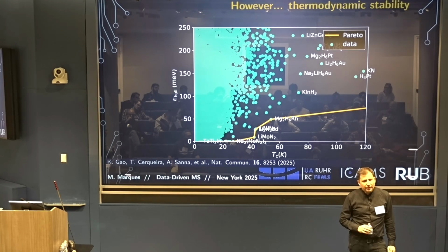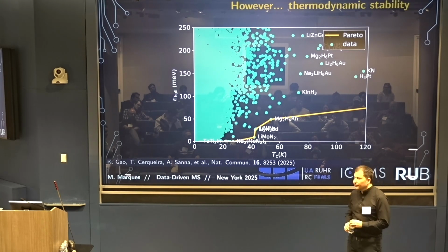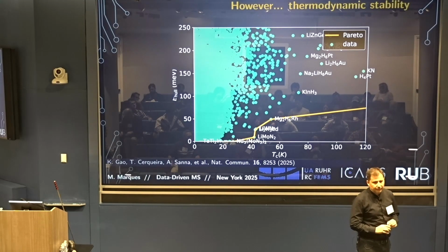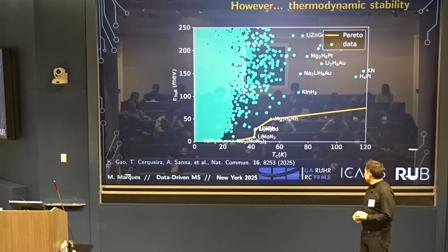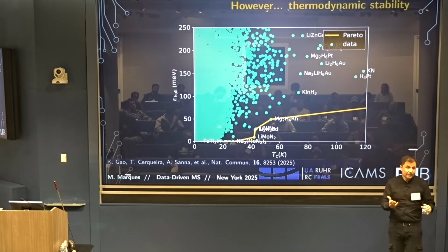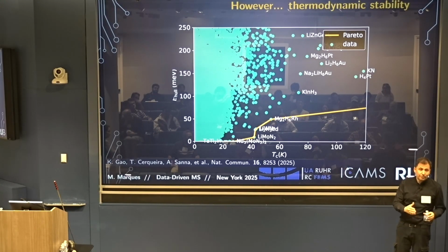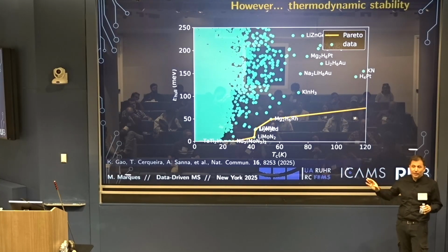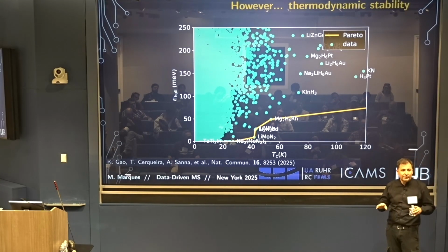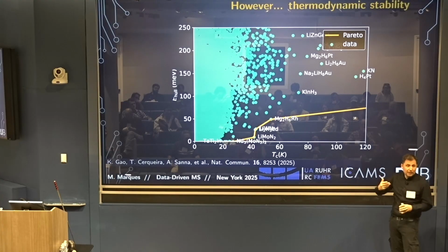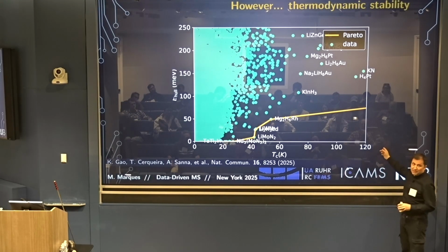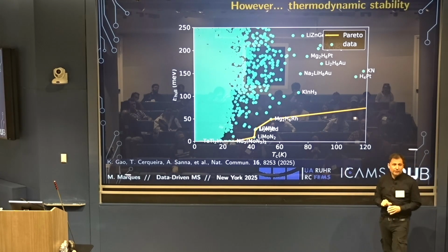Good. So we did a lot of analysis. We spent a lot of time, it's a rabbit hole, trying to find the highest possible TC. And we are absolutely convinced, from the data, not from the mathematics, because if you go through the mathematics, probably the limit for TC is 1,200 Kelvin for electron-phonon coupling. This is, I think, the mathematically correct number. But from the data, from the alpha square F of omega that we have, the absolute limit for TC cannot be much beyond 100 Kelvin at ambient conditions.